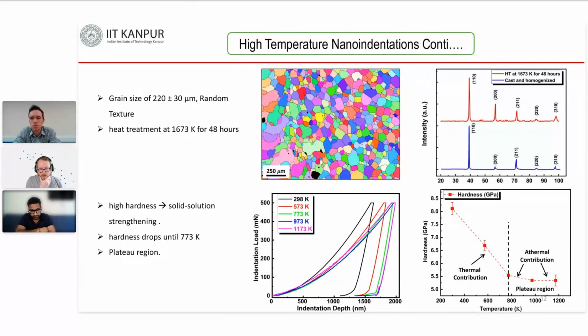Just further on from that, Andy, what sort of calibration frequency would you recommend for high temperature indentation tips? Would it be before any indentation cycle? Yeah, basically before and after every indentation cycle. Certainly if it's a relatively hard material, just to keep track of the tip shape. We have even mounted a calibration sample such as fused silica along with the sample tested during a high temperature schedule, so we can perform reference indents between temperatures. That's not always really necessary, but it is important to keep track of the tip geometry when doing tests at very high temperatures. Yeah, absolutely. Definitely key to keep track of that, because really without it you have no usable results, as you said. Yeah, absolutely. Okay.